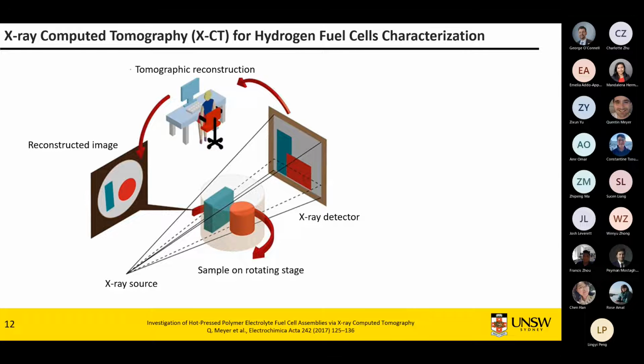Yeah. So the technique I use a lot is called X-ray computed tomography. X-ray computed tomography is basically like doing an MRI of your body, but instead you put a small sample in an X-ray machine, and then you basically rotate it through 360 degrees, and then you do some bit of processing, and you get a 3D image of your sample.